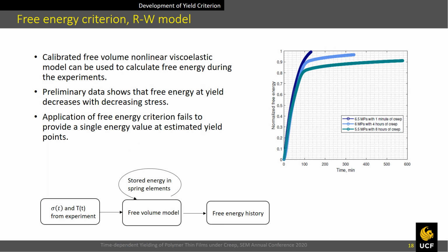The calibrated free volume nonlinear viscoelastic model can be used to calculate free energy during the experiment. Preliminary data shows that free energy at yield decreases with decreasing stress. Application of the free energy criterion fails to provide a single energy value at the estimated yield points.